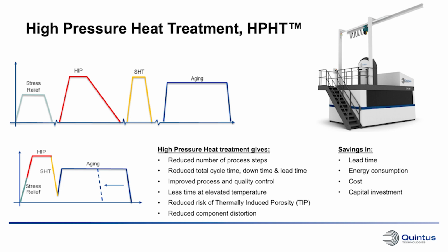Right. Okay. Cool. So on the cooling side, are you also doing aging in the HIP after the solutionizing steps? Yeah, of course it's possible to perform aging because you can heat the furnace, and if you require a certain temperature for a certain time, you can leave the parts in the furnace. So you can actually do quench and tempering as well, I guess, in stepwise up and down. Yeah. Okay. Also very interesting.